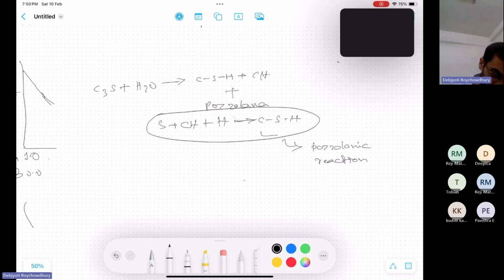Silica fume is derived from quartz. I also mentioned all this in the PPT, and I will share it with you. For silica fume, quartz is heated to 1800 degrees Celsius to make pure silica, which is in gaseous fume form and gets condensed, and after condensation microsilica is formed. Microsilica has the potential for providing high strength in concrete. Rice husk is also a pozzolana. If you burn it, the CO2 will evaporate, leaving siliceous and aluminous material. Now another part I want to discuss.